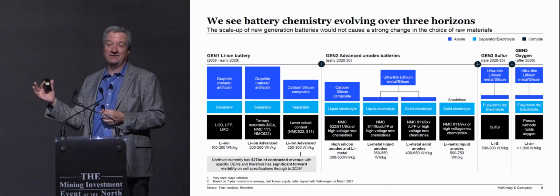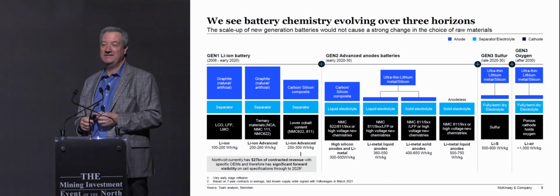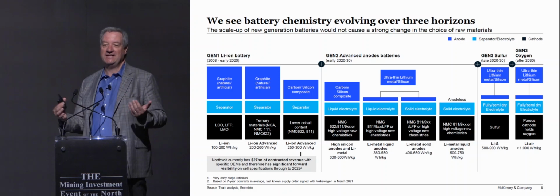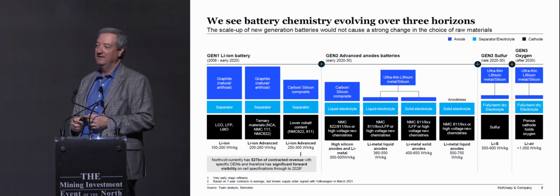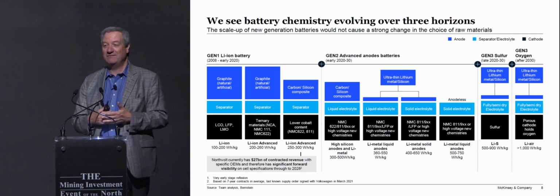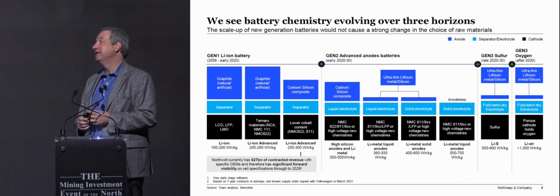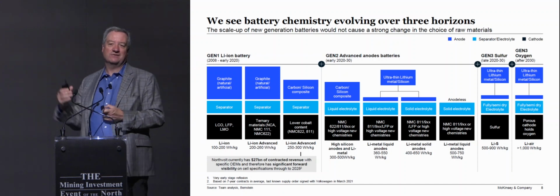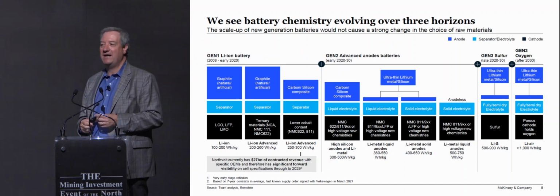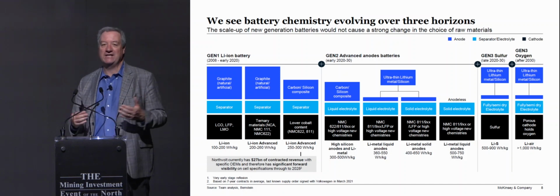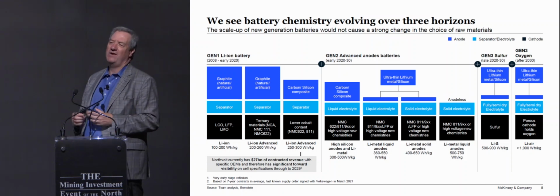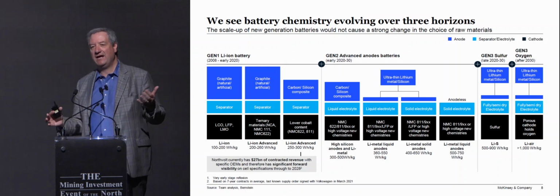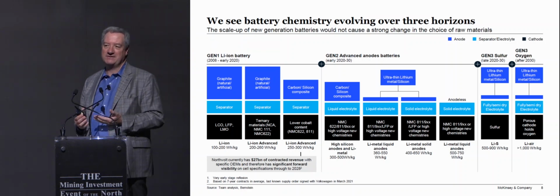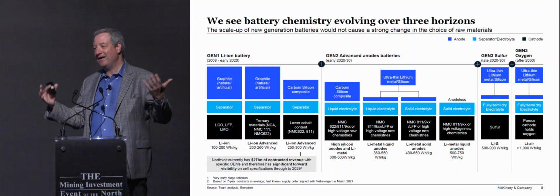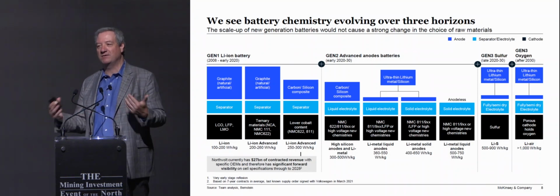The best material in a battery for a lithium-ion cell is lithium. So you use a thin sheet of lithium, ridiculously light, down to as low as, we've heard, 3 microns. And lithium in the battery would rather travel to lithium than anything else, so it's incredibly efficient. And how do I have a lithium metal anode? The first thought was I need a solid-state battery, because lithium just degrades very, very fast. How do I get a car that's going to last 500,000 kilometers with a battery that lasts? Lithium metal in today's battery wouldn't last 10 kilometers. It just falls apart almost instantaneously.